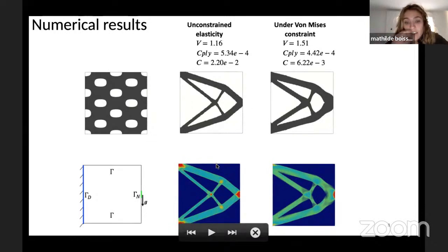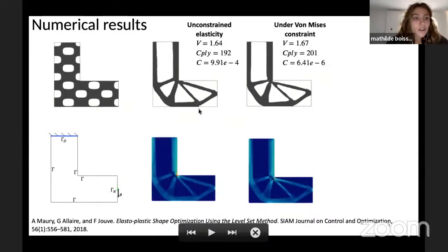But if you compute the elastic stress that corresponds to this figure, you see that it's very high in the middle and in these corners. And the von Mises function of this elastic stress is actually higher. It's getting out of the elastic domain. And when you add the non-plasticity constraints, you see that the bars are getting thicker. But on the other hand, the von Mises function of the elastic stress is lower than before. And so you don't have any plasticity or these kinds of deformations that might result in low cycle fatigue behaviors. So that was for the first part, but now, oh no, I'm sorry, I forgot this test case.